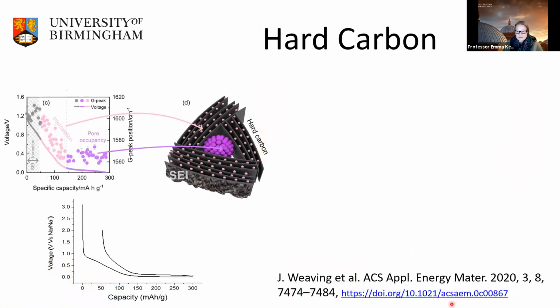We also did some work with UCL and Julia Weaving, who also showed some really nice work which confirmed what we saw from the MRI from Raman, where we got an SEI formation at the beginning, got intercalation in the sloping voltage profile, and then this pseudometallic sodium occupancy at the bottom plateau.